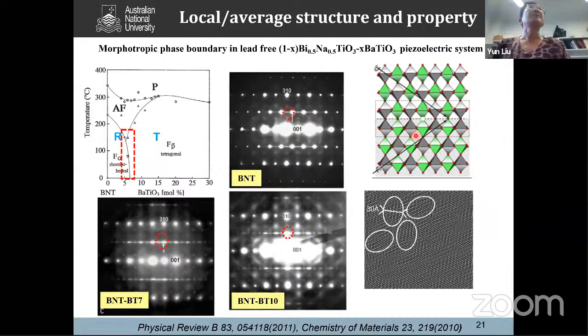So that until you see the diffuse scattering, this is a straight line. That's these atoms moving along the one direction. The ion displacement like bismuth, sodium, titanium. But if you see the diffuse scattering here is different in comparison to this one, this diffuse scattering indicated the long-range ordered 111 direction in the rhombohedral structure has completely broken, and they switch to tetragonal. So what happened here in this boundary is within the boundaries, no average structure change. Instead, it's the local intergrowth structure gradually changing in size, in correlation length, which makes a contribution to optimal performance of the piezoelectric property. Okay, until at a certain point, this structure is completely damaged.